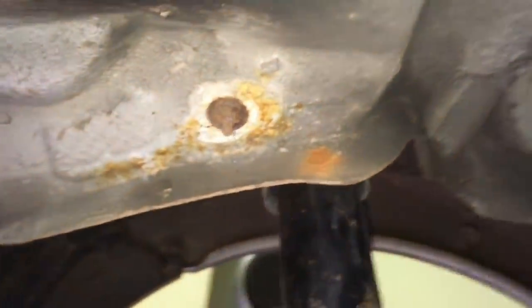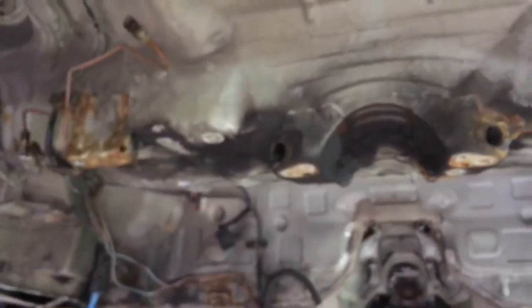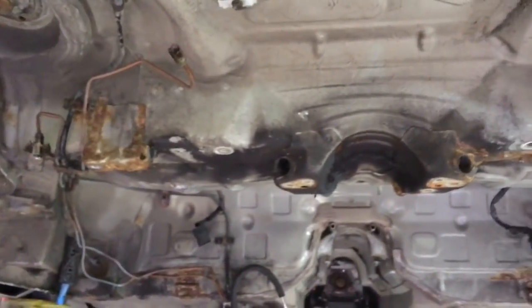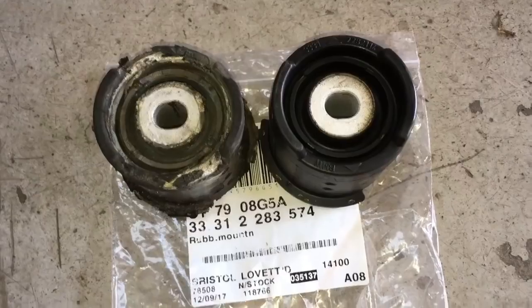Definite crack there, possibly a blown spot weld up there, and then our common spot weld breakages on the side panel, maybe a move in there as well. And now we could probably see the crack in the seat, or the split in the seam sealer, to suggest that the panel's been moving slightly away from the wheel arch panel. So next stage is to degrease the entire panel underneath and start identifying the cracks.